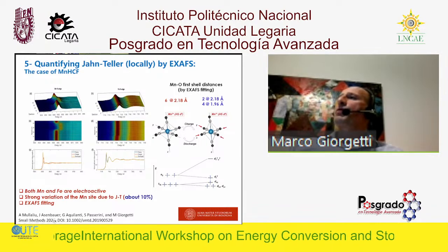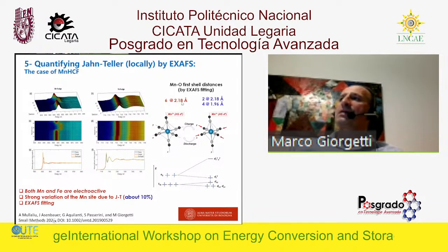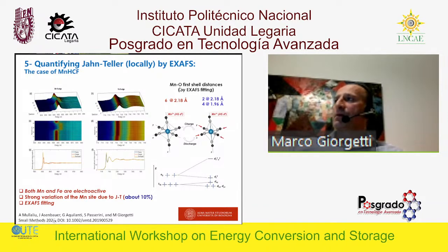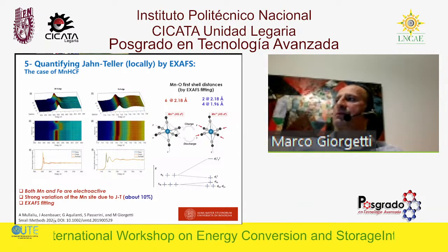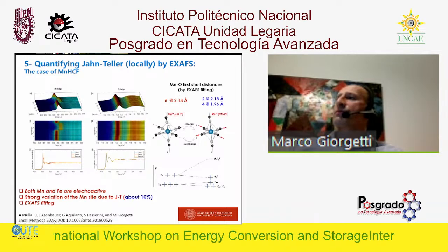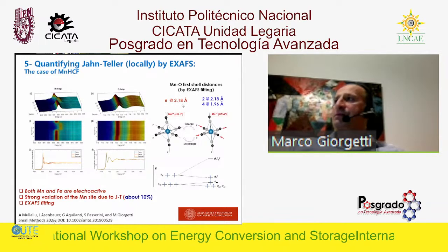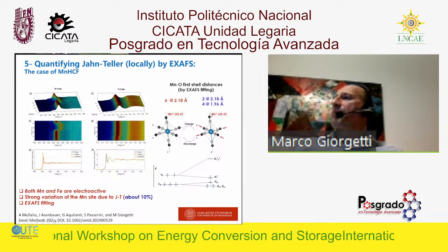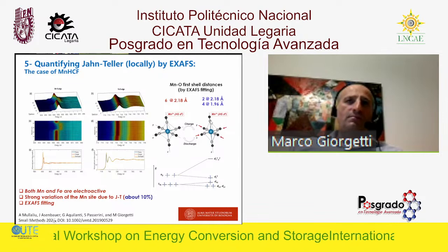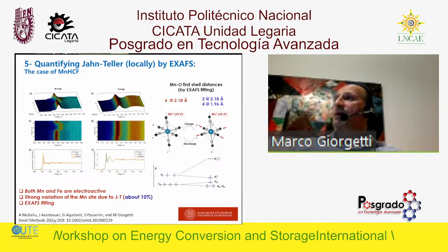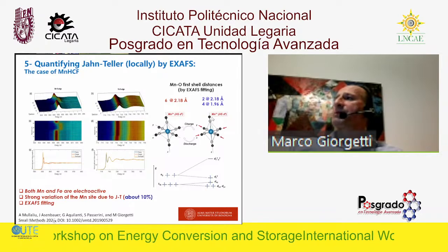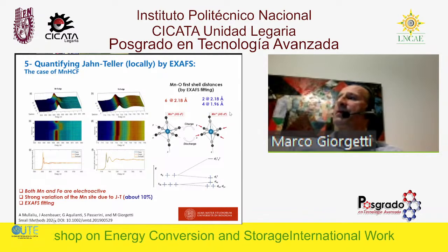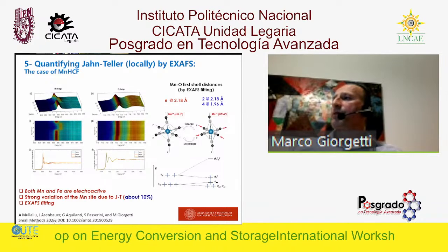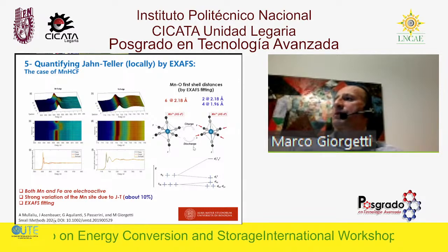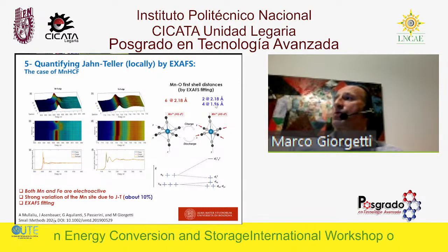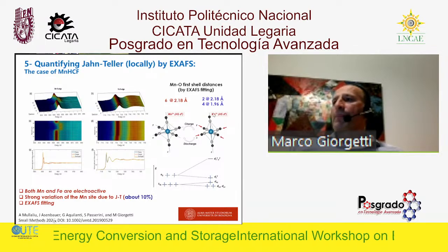So this is basically the figure of manganese-O6 at 2.18 angstrom. The manganese, it's oxygen, the first shell distance. This is an error. And then it changes from this very ordered picture, because it's a perfect octahedron, to basically this elongated one. So it's, of course, due to the Jahn-Teller. So basically the two apical distances remain at 2.18, and there is a lot of shrinking on one of the equatorial plane. So this is during charge and discharge, charge and discharge. This is a huge variation anyway in the first shell contribution.